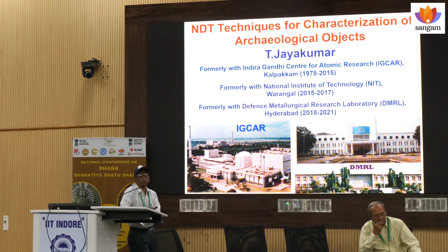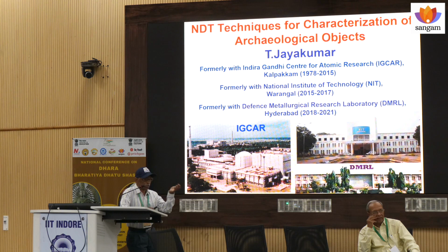And also in the Delhi Iron Pillar, we feel that there is gold at one of the regions. That also I will show you, how we have interpreted this. And also the thermomechanical processing, it would have gone through at different regions, and the structures what you see through in situ metallography also indicate that the temperatures and strains and the cooling rates, in addition to the composition variation from place to place, would have played a significant role with respect to the microstructures that are generated.